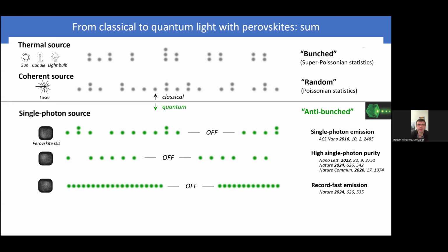Yeah, that's a very good question. It's always a question for any quantum dot material. You have a high surface to volume ratio, you have a small entity. We are a bit protected by this so-called defect tolerance, meaning that lack of some ligands at the surface does not kill the emission as it does for cadmium selenide. So cadmium selenide is a very poor emitter without an epitaxial shell. Here we don't need that. But still, specifically for perovskite, a highly polar solvent or moisture is a no-go. So we cannot disperse them properly in water. We don't necessarily need to, but for some applications that would be needed. And long-term exposure to moisture may compromise their emission as well. So that we mitigate by embedding them into polymers or by encapsulation techniques. So long story short, moisture is the main issue for the long-term stability.